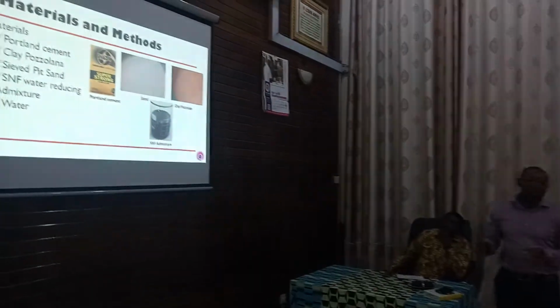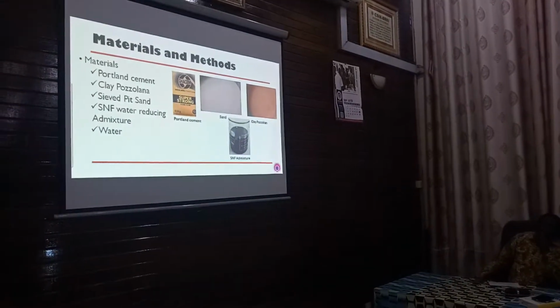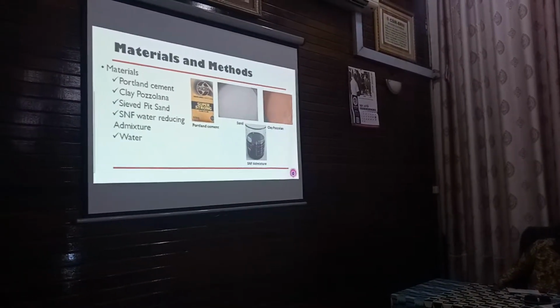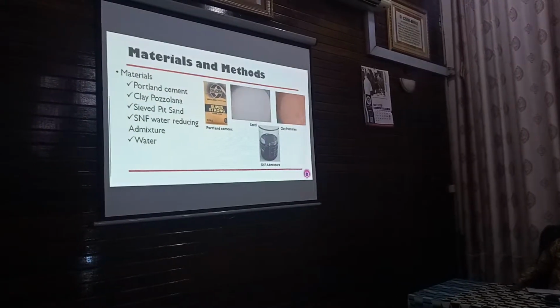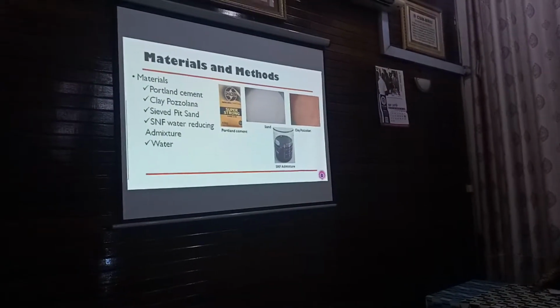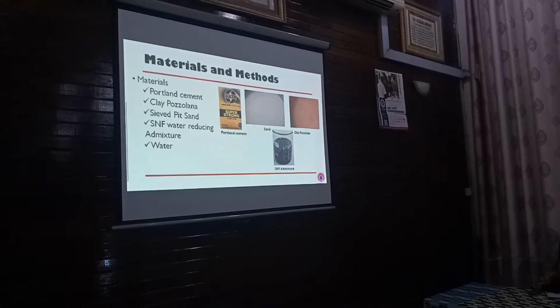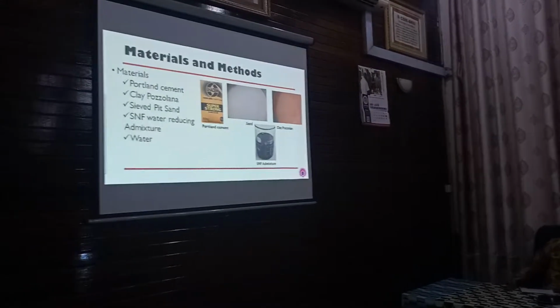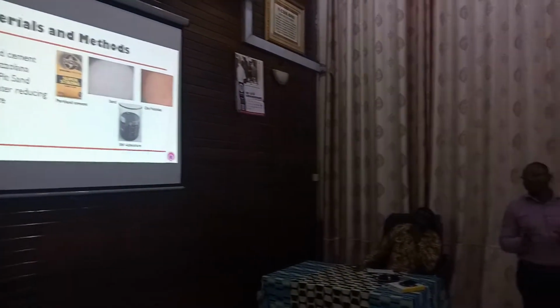So these were the materials that I use. Portland cement, normal grade 42.5 R. Then I use the clay pozzolan. We produce it in the factory. Then I sieve the pit sand. Now SNF means sulfonated naphthalene formaldehyde. It's a chemical admixture. So it is a water reducing chemical admixture.